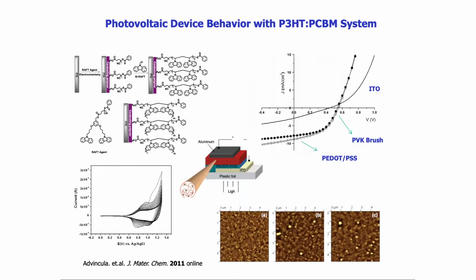Or in this case of this photovoltaic device, involving again a grafted polyvinyl carbazole using a CTA or RAFT polymerization to graft the polymer brush, we then prepared a bulk heterojunction cell device made up of polythiophene and PCBM. The result is we got an efficient device with the PVK brush grafted on the surface, similar to what we would have gotten with a PEDOT:PSS hole transport material, as compared to an ITO without this grafted layer.